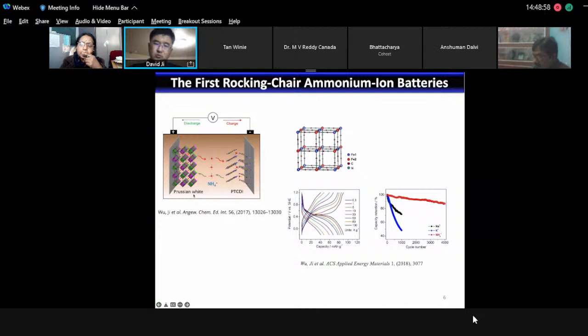And you can use Prussian blue, Prussian white. These are the same thing. It's just, this one is a more reduced form of Prussian blue analog. And we found that big ammonium ion fits Prussian blue better than slightly smaller potassium and a lot smaller sodium. So big ions fit big voids better. So why won't small ions fit? Because small ions in aqueous electrolyte bring solvation with them. Small ions are solvated, in this case, hydrated. They bring in water molecules. The water molecules interact with the host, which is destructive. So that's another thing I want to share.